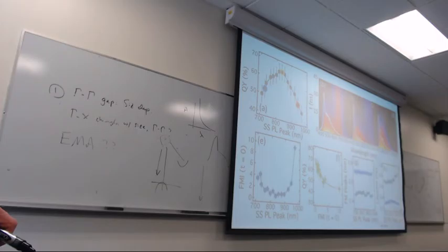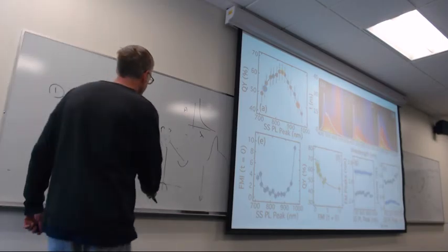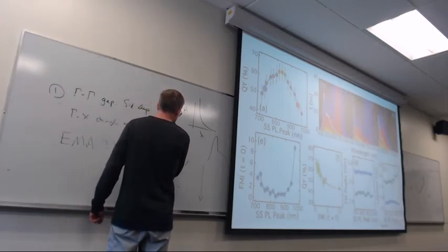Your emission from the main band, which you call bulk, and indirect, means it should be, like in bulk, not optically active at all. It is forbidden because of momentum conservation. But in your case it is active because it jumps from X to the K point, a substantial change of momentum that needs to be taken by someone. Don't forget about that, right?